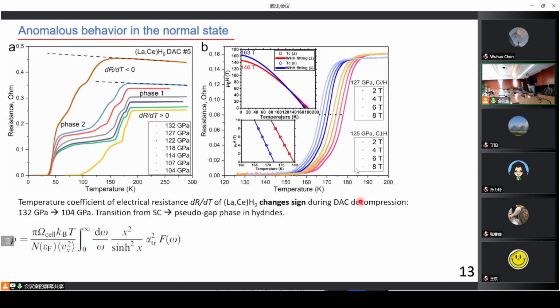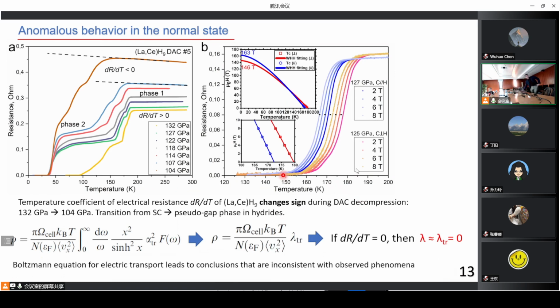If we try to apply classical theory based on the Boltzmann transport equation to this case, we find that this coefficient should be proportional to the electron-phonon coefficient, the electron-phonon strength. In this case it's transport, but it's usually very close to the superconducting electron-phonon interaction strength. And at the particular points where this derivative goes to zero, it means that there is no electron-phonon interaction, so lambda should be close to zero. Electron-phonon interaction should disappear in this material, but that is absolutely inconsistent with the superconducting transition observed in polyhydrides, which is usually explained by electron-phonon interaction and by Bardeen-Cooper-Schrieffer theory.